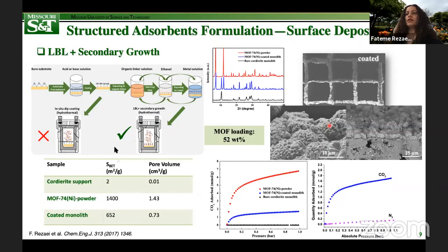In addition, like their powder analogs, the coated samples exhibited high affinity towards CO2 relative to nitrogen, although the obtained capacities were lower than those of powders, as you can see here. However, by controlling the number of layer by layer steps, as well as dipping time and temperature, the adsorbent loading and film thickness can be controlled and tuned.